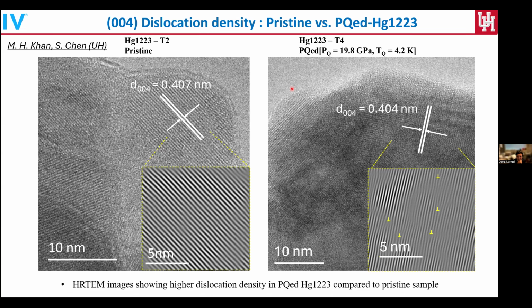So it may sound a little bit weird, because normally for superconductivity, talk about disorder, defects, dislocations, they're not really in favor of superconductivity. So here we want to break up these two questions I mentioned earlier. The reason that helps to enhance the TC may not be the reason that helps to retain the enhanced TC.